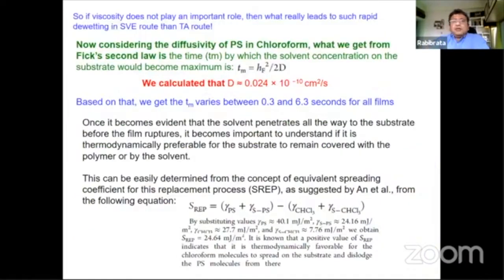So then we started to look into certain additional issues. One of them is, in solvent vapor exposure, what happens? What happens is ultimately the solvent molecules are penetrating through the film. So it's a process of diffusion. So from Fick's second law, Anuja did some calculations and we came up that the time for the solvent molecules, so the concentration of the solvent molecules, to maximize at the interface is roughly of the order of the film thickness squared divided by 2D.